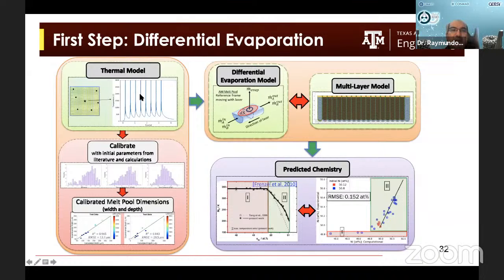So once we calibrate the model, we use it to predict the differential evaporation in a given material for different processing conditions. Then we try to expand this in a multi-layer model to take into account building the different layers into a part. And we have actually verified the model. It turns out that, as I said before, nickel titanium is very insensitive to changes in composition in this region, but very sensitive here.